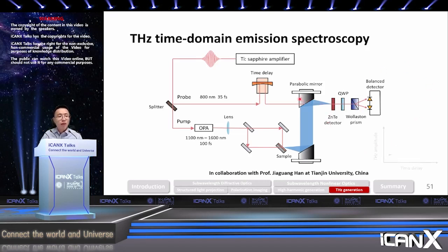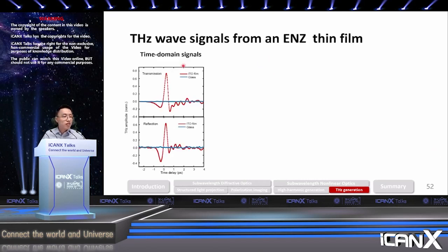By scanning this delay stage, we can generate a time domain waveform of the terahertz signal. So this is our experimental result. For the time domain signal, both in transmission and in reflection configuration, we are seeing this very narrow pulse with a pulse duration of less than 1 picosecond.